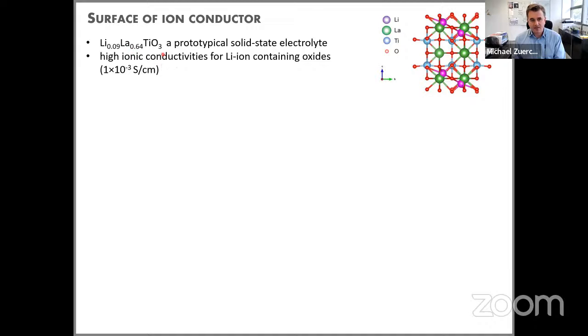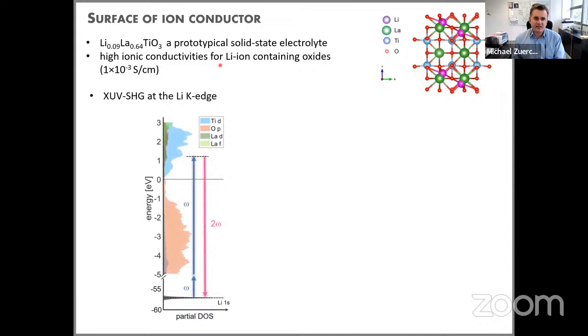LLTO is known to have a very high ionic conductivity. Basically the ions hop within these LLTO cages. What we were interested in studying with XUV SHG, in comparison to X-ray absorption spectroscopy, is what we can learn about the lithium at the surface of this electrolyte, as a first step towards possibly measuring an operando battery down the road. So this is the general idea.